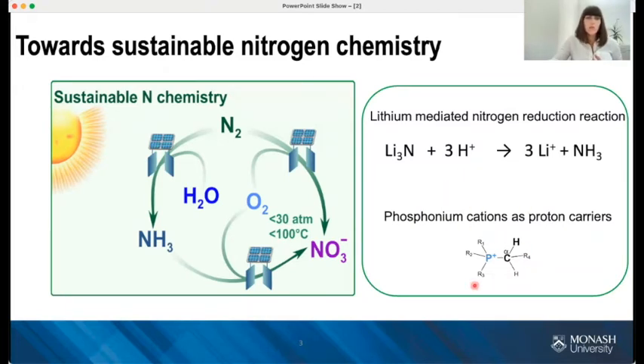And one example is the trihexyl tetradecyl phosphonium cation. These types of compounds are known to have good chemical, thermal, and electrochemical stability. And additionally, they can dissolve high amounts of nitrogen, which was presented by our group a few years ago. And this is very important for nitrogen reduction, to actually have this high solubility of nitrogen.